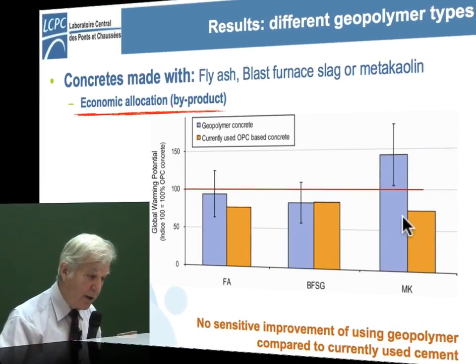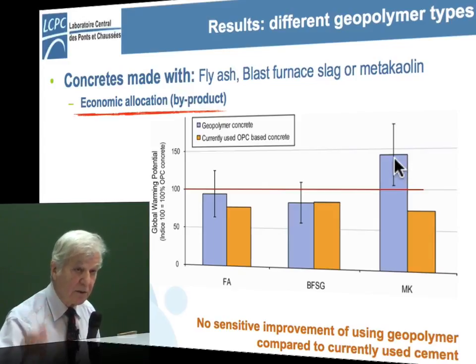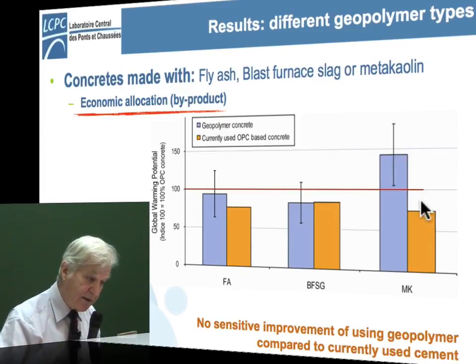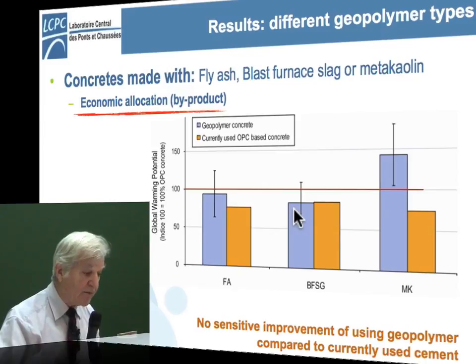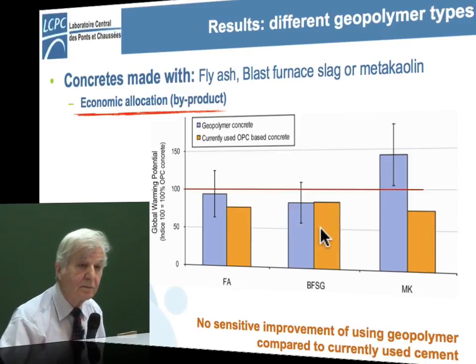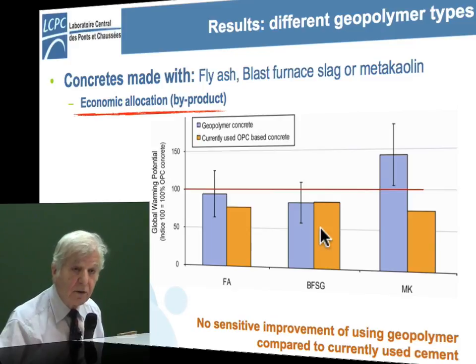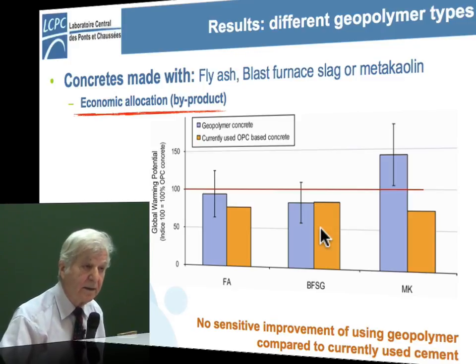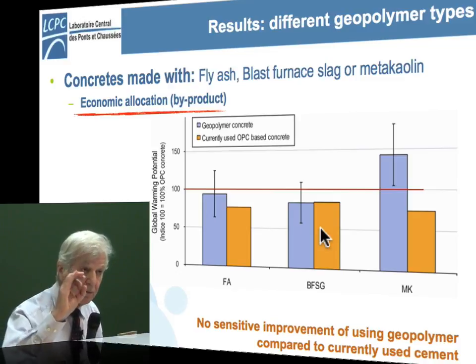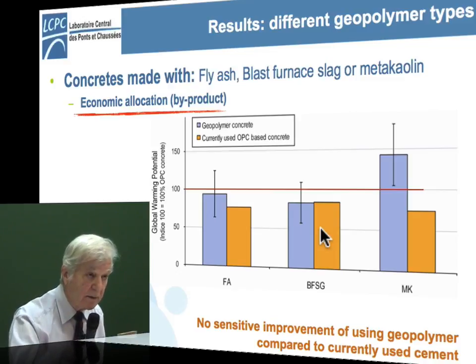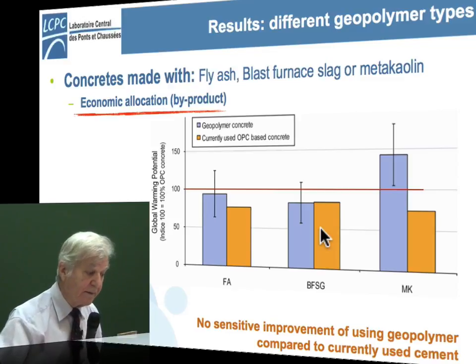So still comparing with metakaolin, obvious nonsense, but still having 75. Blast furnace slag and Portland equal, wrong, because 100% blast furnace slag is not a geopolymer cement. It is simply alkali activated slag, and this is not stable. Long-term durability, 0. So it is not a cement. It is not a geopolymer cement.